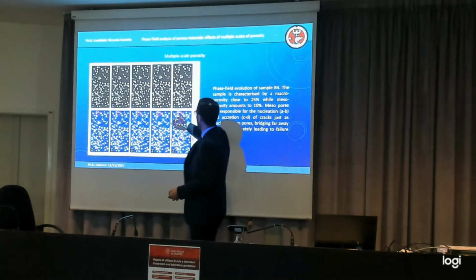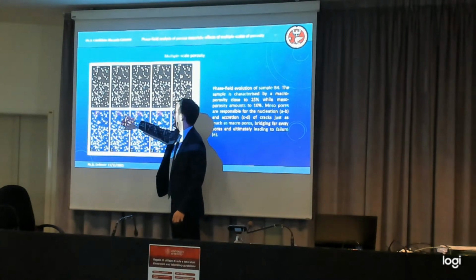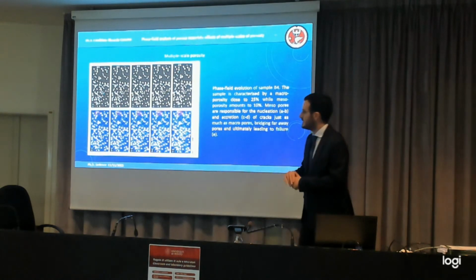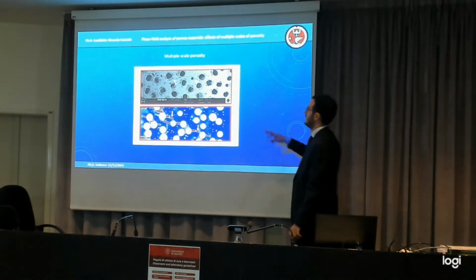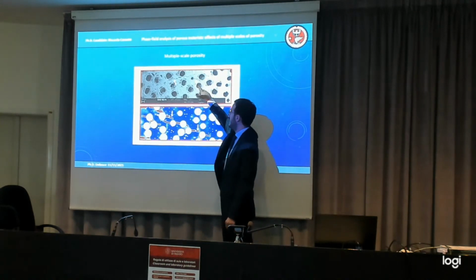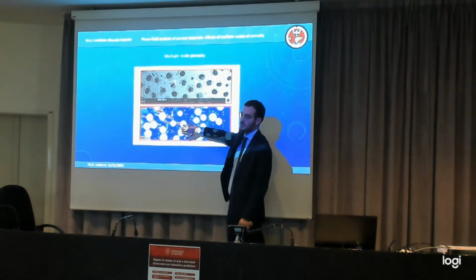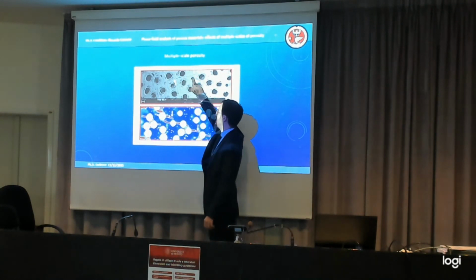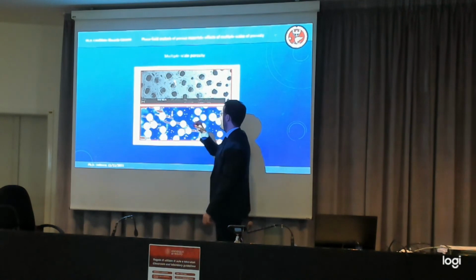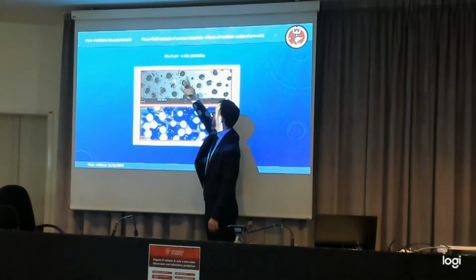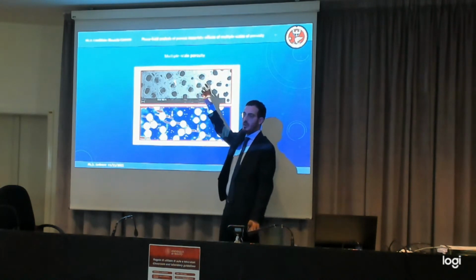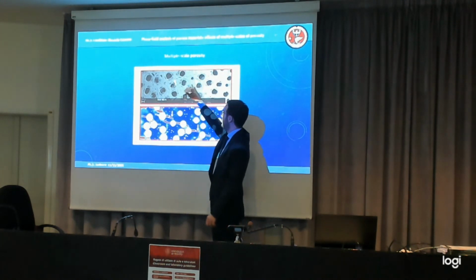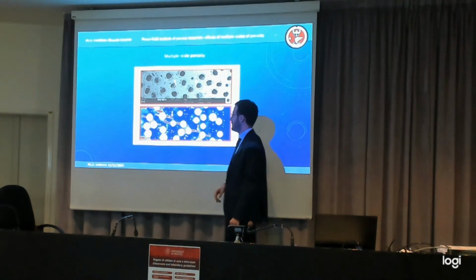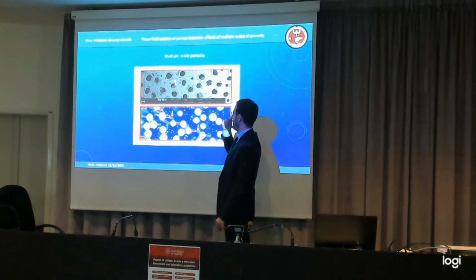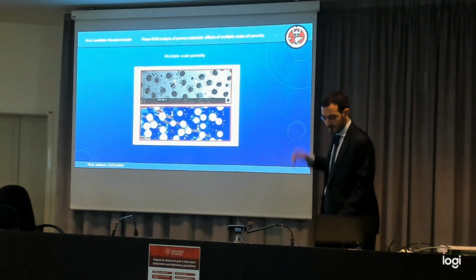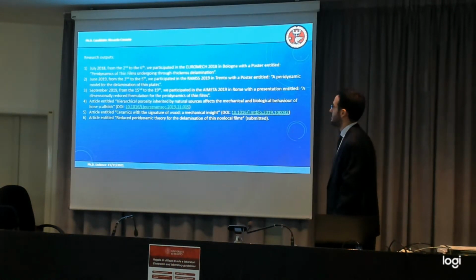So this is a small picture, but it's possible to see that small pores are actually able to develop cracks. And this is something that is happening in bioapatite, for example, which has multiple levels of porosity, and all the mechanisms of fracture are perfectly reproduced by the phase field model. There is nucleation and development from micropores, and also from the macropores. So macropores and micropores are both responsible for crack developing and crack branching from one onto the other, and the model is able to reproduce it. This is for two different geometries, but the capacity of the model is well established.